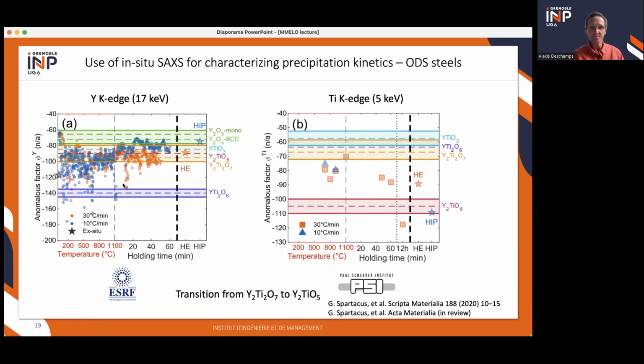and compare it to different stoichiometries that you could guess. And actually, at the end of the heat treatment, at the beginning, it varies somehow. At the end, it becomes quite compatible with the two main candidates that you expect, which are the two phases here, Y2TiO5 and Y2Ti2O7. So it's quite good that you end up at this point, but you're still not able to discriminate between the two because basically they have the same yttrium composition, more or less.